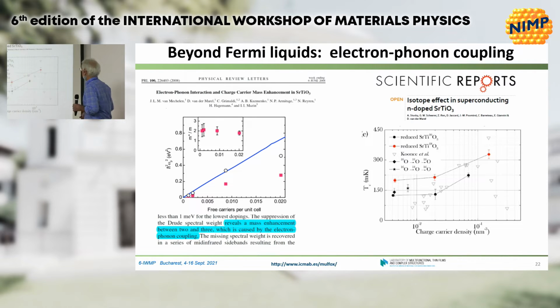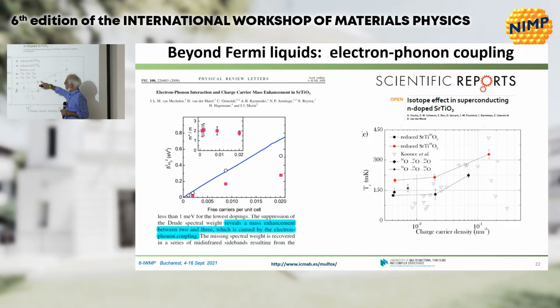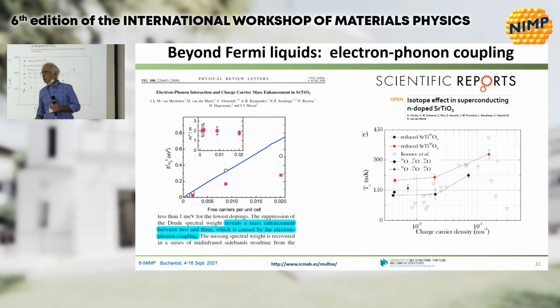And another and more beautiful experiment, which just recently appeared in Scientific Reports, is the critical temperature of n-doped strontium titanate. N-doped strontium titanate is superconducting at low temperature. You change the isotope from oxygen 16 to oxygen 18, and the critical temperature changes. Obviously, the electrons are coupled to the lattice, no doubt.